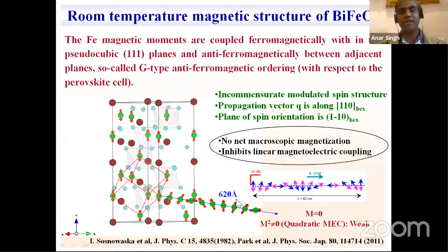So in addition to the G-type antiferromagnetic structure, there is also a cycloidal spin structure which has a periodicity of 620 angstrom. And we can see that for every plus spin, there is a minus spin. So net magnetization over this scale is 0. If magnetization is 0, then we don't have a linear magnetoelectric effect. In bismuth ferrite, we can have only a higher-order magnetoelectric effect. That's why the magnetoelectric coupling in bismuth ferrite is weak. So in order to improve the magnetoelectric coupling, we need to suppress this spiral spin structure so that we can have non-zero magnetization and we can get a linear magnetoelectric effect.